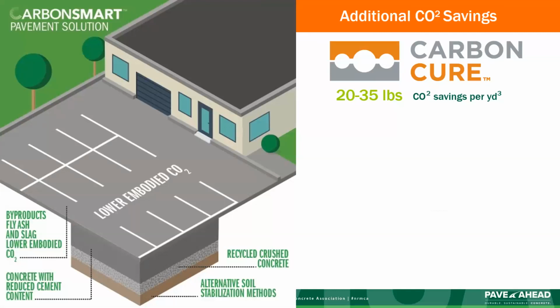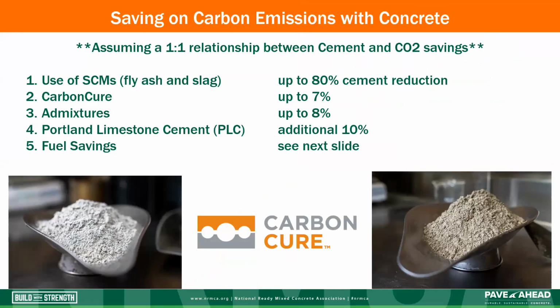In addition to some of the CO2 reduction strategies we have already examined, CarbonCure has found that an additional 20 to 35 pounds of CO2 can be mitigated by injecting carbon dioxide into concrete during the mixing process. Depending on the application, these reductions can be achieved by using one or any combination of these strategies, so you're not limiting yourself to any one. They can be combined to maximize or optimize your concrete mixture.